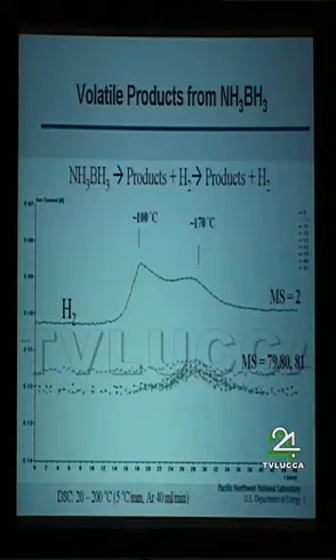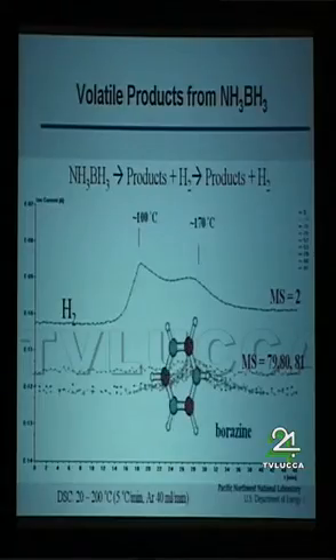And what's interesting is the borazine does come off with the second step. With hindsight, that's probably not too surprising. If you wanted just 6 weight percent from the material, then you could completely avoid the borazine by not going to too high a temperature. And I think I have a pretty picture of the borazine here. But if you want to get more hydrogen out of this, you've got to be more creative and figure out ways to minimize the borazine formation if possible.